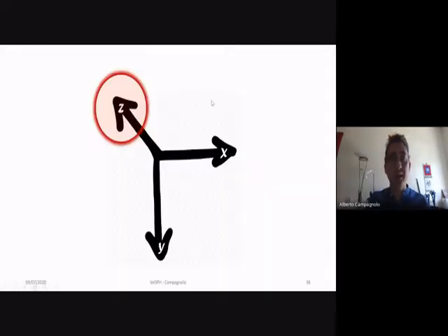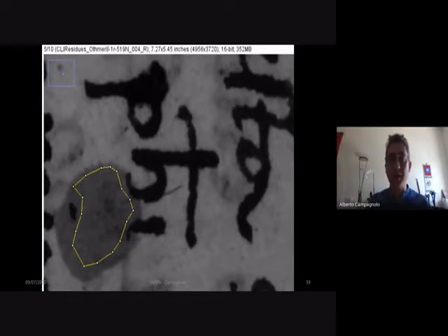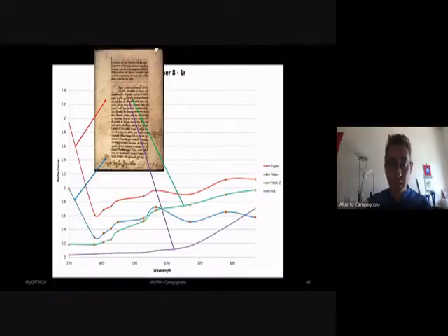So we can start using the third dimension in order to get information throughout the full stack of images, not just looking at how one material disappears on the infrared and appears on the UV, for example. And you can plot this information to understand how the different materials react differently. On that page, we did some spectral curves, and you can see how the paper, the inks, the blemishes of the object all react differently to the light. And we can basically just find numerically the luminance, reflectance actually, of each pixel or area, and plot that.